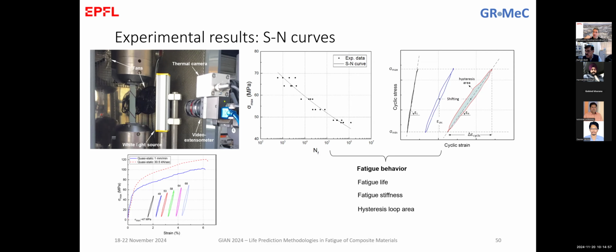During the loading, you increase the temperature. If you let it go without the chamber, the temperature at the end might go to 80 degrees. So your specimen fails, but not in an accepted way, because it is softer.